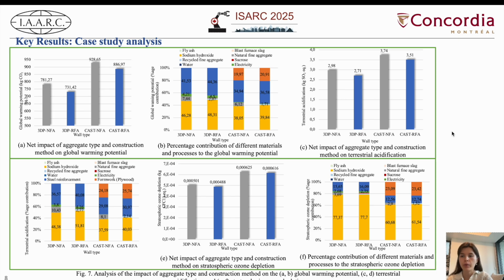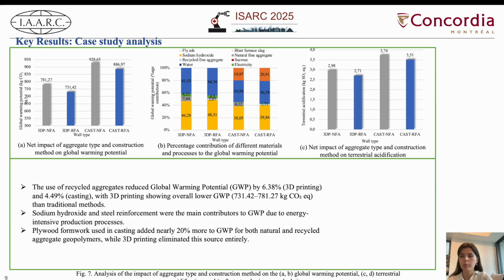In our case study, we found that the use of recycled aggregates reduced global warming potential by over 6% in 3D printing and about 4.5% in casting. Among the two methods, 3D printing consequently showed lower global warming potential, primarily because it avoids the use of plywood formwork, which added nearly 20% extra emissions in the casting process. We also observed that sodium hydroxide and steel reinforcement were the main sources of environmental impact due to their energy-intensive production process. Overall, 3D printing with recycled materials not only performs well technically, but also significantly reduces environmental impact, especially in terms of global warming, acidification, and ozone layer depletion.